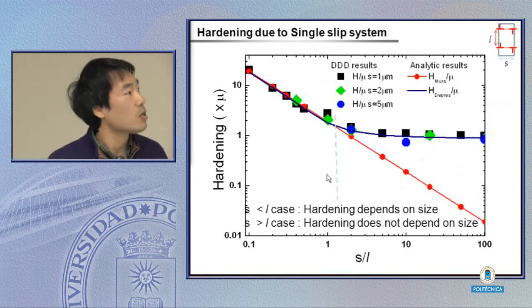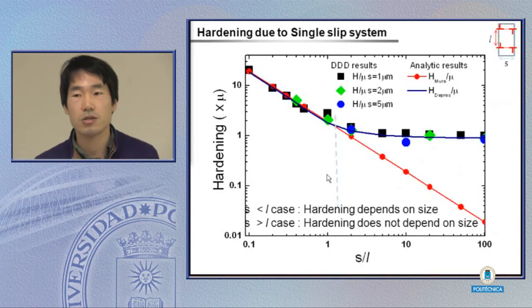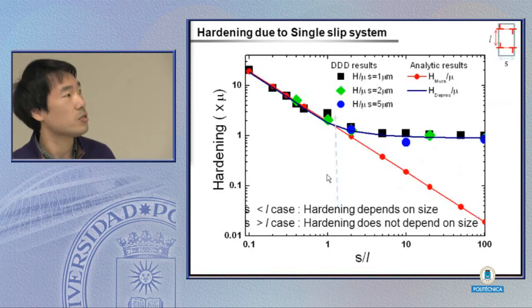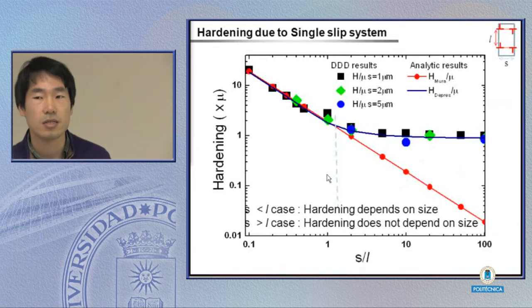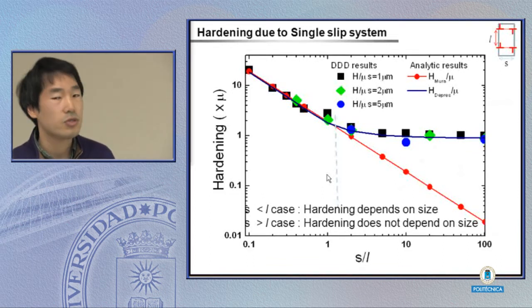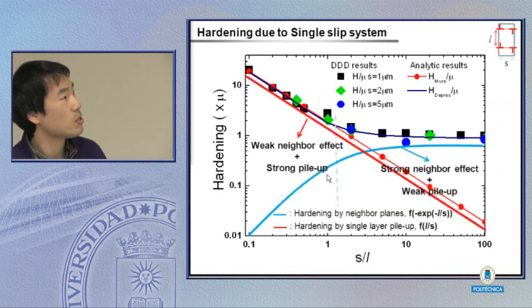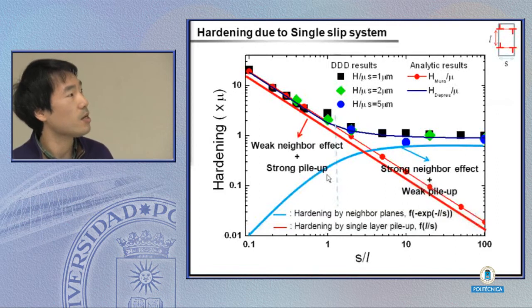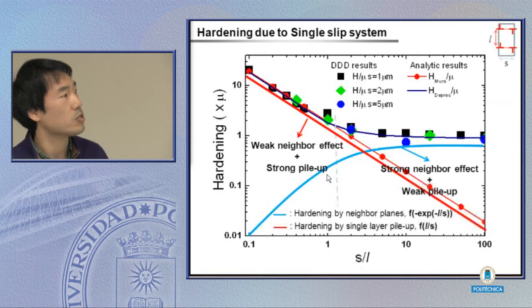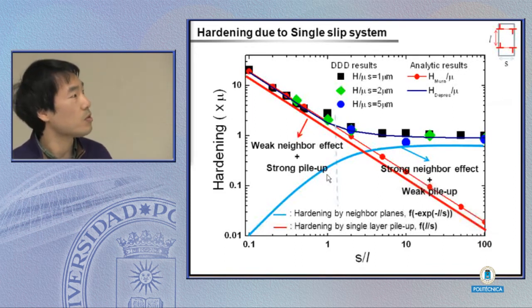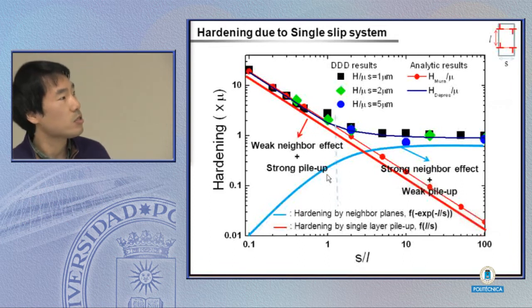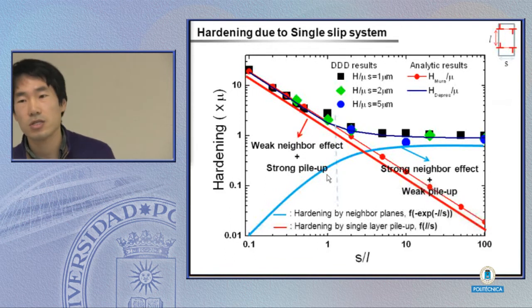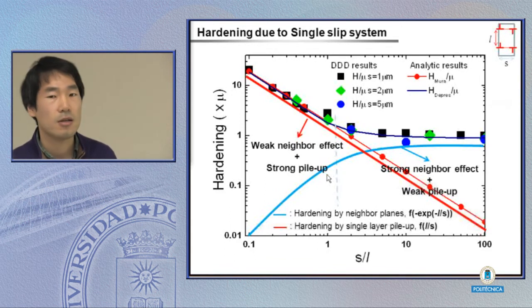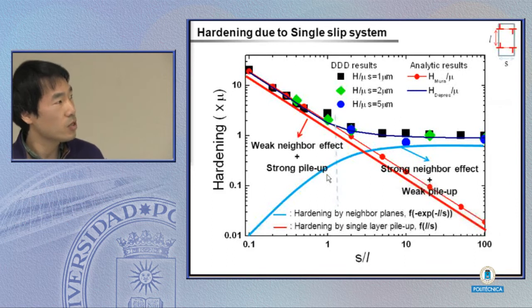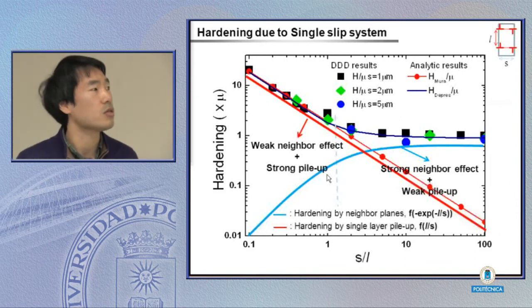At first, here is the work hardening result. As you can see, the work hardening totally depends on the ratio between two length scales, the material size and internal size. And there are two regions. At the first region, the dislocation dynamics and the Mura solution and the Deprez solution all give the size effect. The smaller makes the stronger. On the other hand, in the other region, both the Deprez solution and dislocation dynamics give the stable hardening, but the Mura solution doesn't match the dislocation dynamics result.